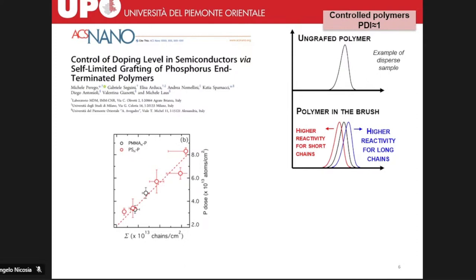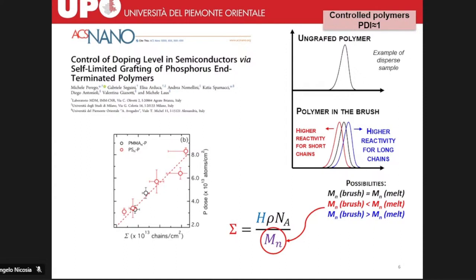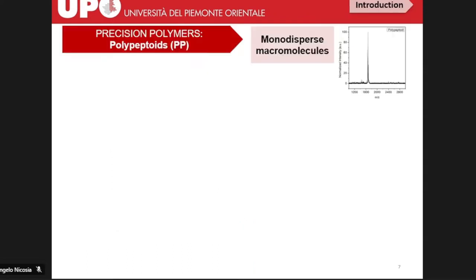So we have 3 different scenarios, and we have found that in general, if we have a polymer with a particular molecular weight distribution, the brush is mainly formed by the short chains that are attached to the surface. So using this equation in this case is an issue because the molecular weight is not a single number, but a distribution of molecular weights. That's why we are proposing precision polymers to try to be more accurate in the doping of the semiconductors. A precision polymer basically is a polymer that doesn't have a distribution, but as you can see from this MALDI as an example, is a monodisperse polymer.